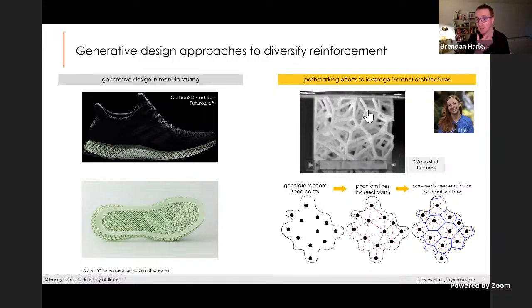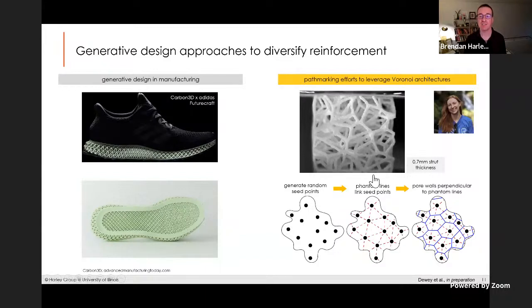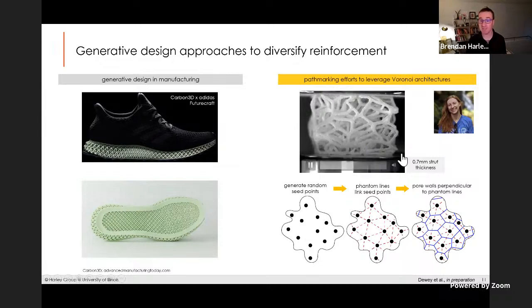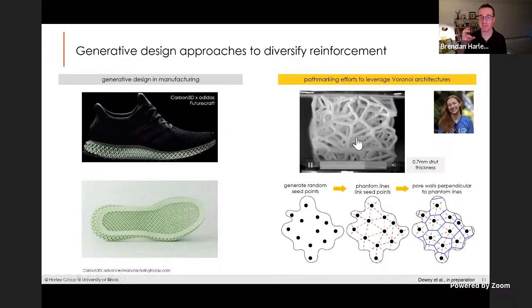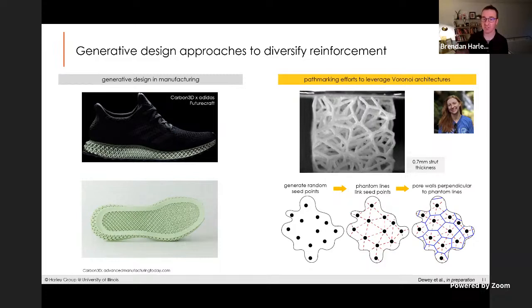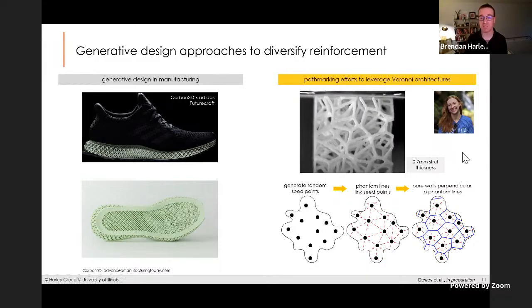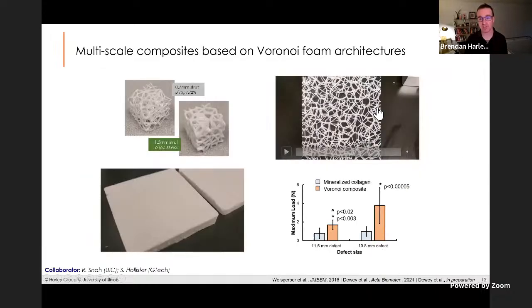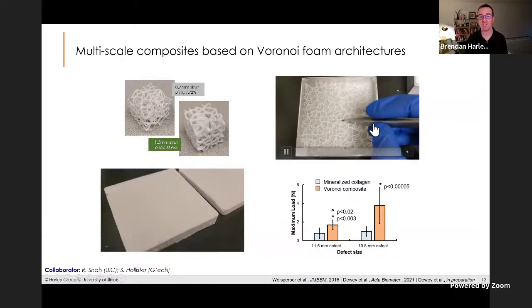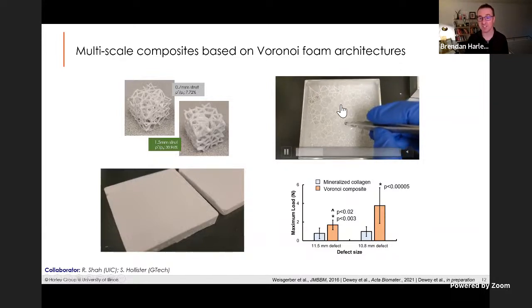These are actually printed in the IGB in one of our 3D printer systems that we could develop these foam architectures. The neat thing is, as you load them, you'll see the fiber starting to bend and buckle and the pores collapse. But these are properties we can control at the millimeter scale that are much larger than the cells in our material. But this is the scale that the surgeon would handle it on. So this is a larger reinforcing structure we're going to be penetrating into our scaffold. And so that's really what Marley had developed. So here's one of these large three-dimensional foam materials that is based on these Voronoi foams that she's printed. She then takes it and is embedding it into the slurry of our collagen suspension and then freeze drying it.